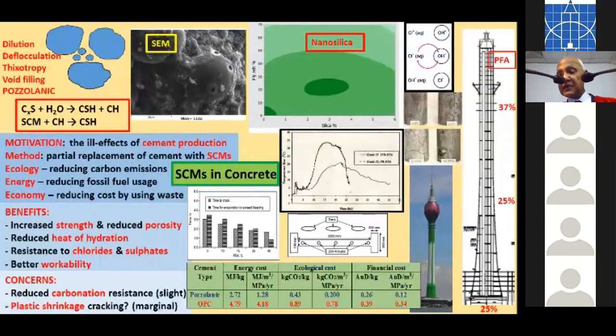So when the Lotus Tower was coming out of the ground, there was discussion as to whether we needed to use fly ash anymore. So our Professor Nanakar at Moratuwa University and I were involved in this, and we said resoundingly, yes, we must use fly ash even above the ground level, because this is in a marine environment, here the Beira Lake, and here we had 25% fly ash used in the superstructure as well as in the foundation. And then finally, the Chinese contractors themselves, when they had to pump concrete to this great height, wanted even more fly ash, which we readily agreed, 37% of fly ash, because there is better workability, better pumpability of the concrete.